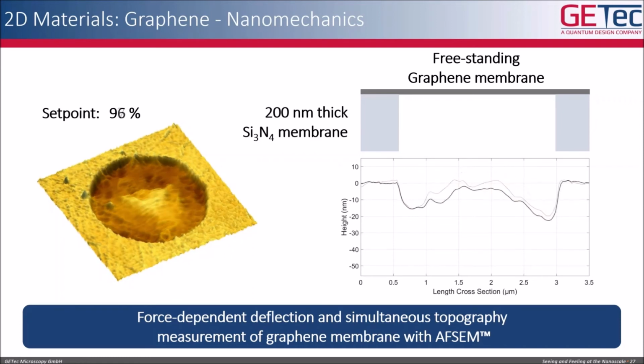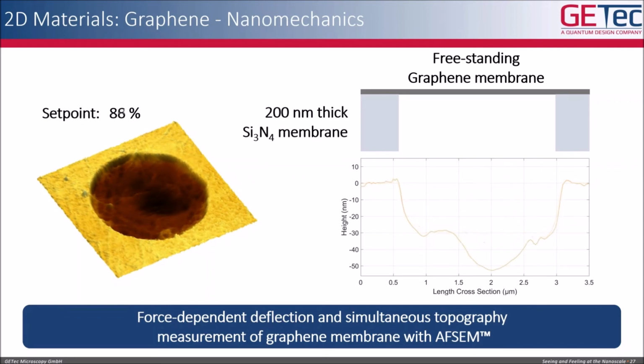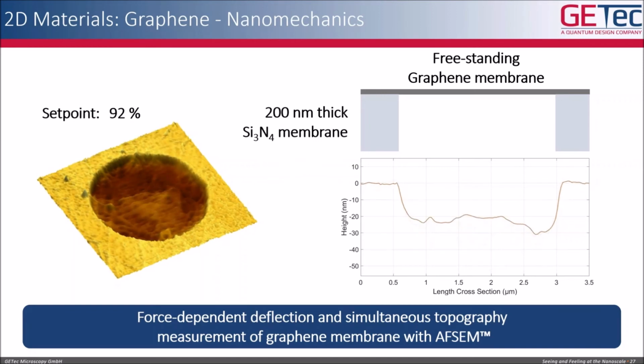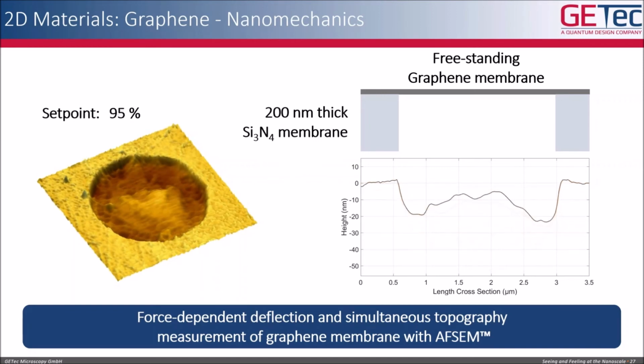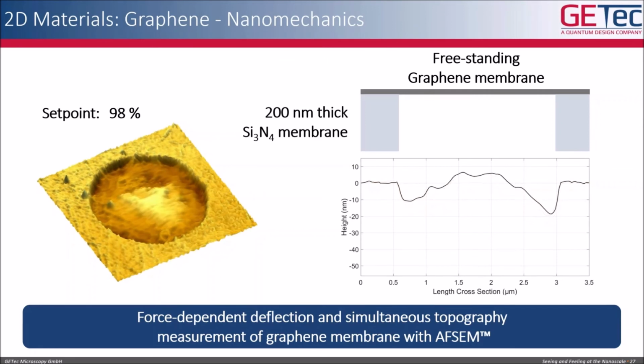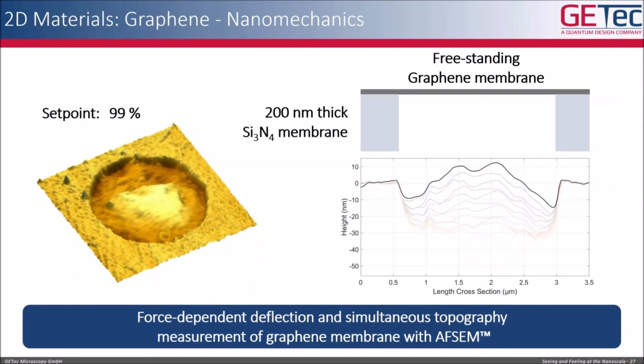Now you see the small animation. When we increase the interaction force, you can really bend down the graphene with the cantilever tip. Then if you lower the interaction force, you see a recovery of the graphene up to its original position. So we can really now use the AFM to characterize nanomechanics of these freestanding graphene membranes inside your SEM system.